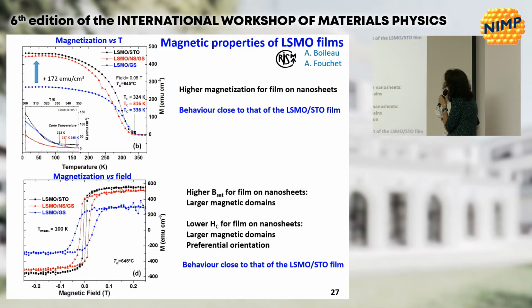The colleagues in Caen have also performed magnetic property measurements, and they have compared the film directly grown on glass here in blue, grown on nanosheets in red, and grown directly on a single crystalline strontium titanate as a reference in black. So we can see that concerning the magnetization as a function of the temperature, the manganite on nanosheets presents a behavior which is very close to the one on the strontium titanate substrate, compared to the film made directly on glass. Also, if we look at the magnetization as a function of the field, we can see that the material grown on nanosheets is close to the one made on the reference substrate. These results are due to the fact that you have larger magnetic domains and also a preferential orientation.